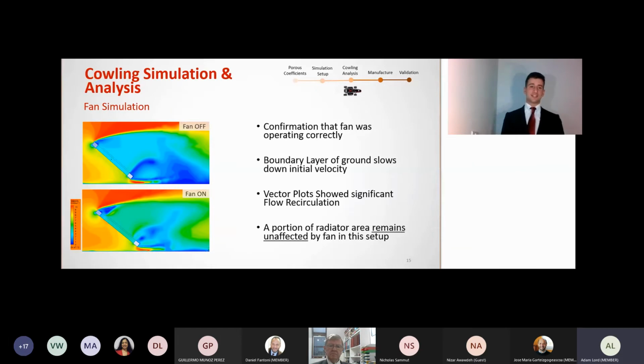The velocity contours were plotted and illustrated on the slide, where the plots show an incident velocity of 10 meters per second in the pre-stream, and then a wake of turbulent air forming behind the radiator. Now, a phenomenon which is quite notable is that when the fan is activated, the area of the radiator which does not fall under the fan's catchment area, so to speak, will not be affected by the fan suction. And furthermore, with the diameter of the fan actually being larger than the radiator's width, there were parts of the fan extending beyond the radiator, and these parts were essentially being wasted. So it was deemed that with the introduction of a shroud, not only will it be shaped to accelerate the flow better through the radiator, but it will also be designed to capture the entire area of the flow.